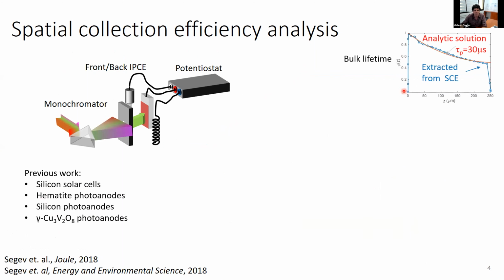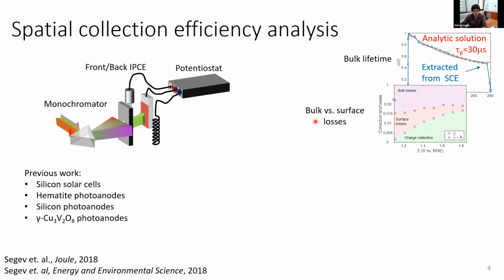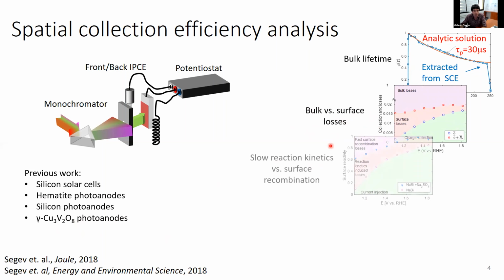results. For example, we can extract, this is fairly trivial, the diffusion length in a silicon solar cell. We were able to discriminate between bulk and surface losses. This was in BiVO4 photoanodes for water splitting. We could also discriminate between slow reaction kinetics due to imperfect chemistry and fast recombination events at surfaces, also in BiVO4.